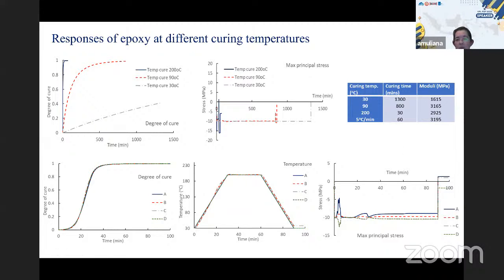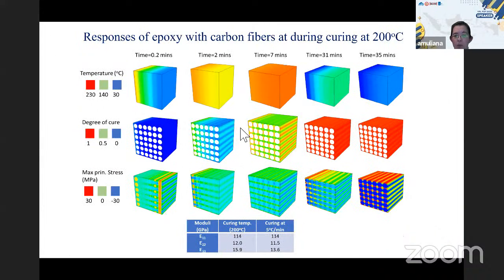Now, when we use this epoxy in the composite, the response will be complicated because of the existence of fiber. This is just to show a simple microstructure when we cure the composite. So in the beginning, we see swelling because of the expansion due to heating. At the end, we see all this shrinkage. This would induce stresses in the material, and that would also affect the moduli of the composite sample, right? So this is where we said, okay, being able to control the curing process is the key of having a good finish of the epoxy and the composite eventually.